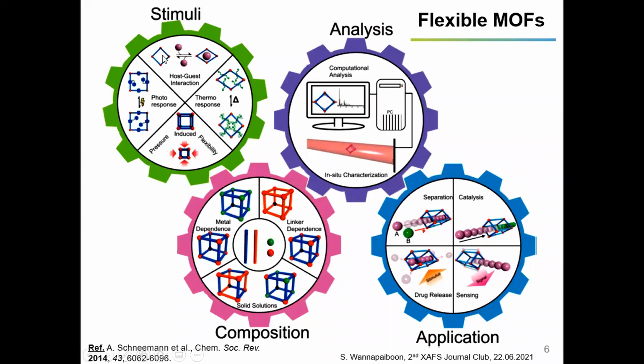It can show structural change under external stimuli, like the addition of gas molecules that induce a structural transformation from a large pore into a narrow pore, or even induction by photons, so photo-responsive and thermal-responsive as well.